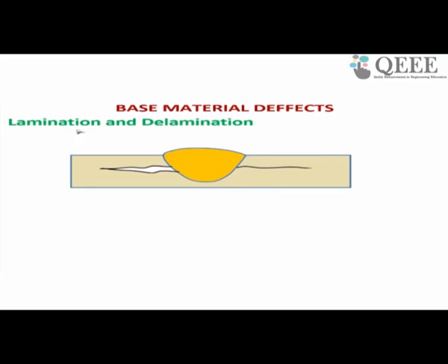Another type of defect is called lamination and delamination. In some cases, you have a base material, for example a laminar type base material. You joined different layers one by one, or you rolled a base material. Inside the base material, we have some inclusions or already some defects. Then with the presence of that defect, inclusion or some second phase particles, when you try to join two pieces, wherever these inclusions are there, from that point onwards the crack will initiate and it will try to propagate. This is called delamination type of defect.